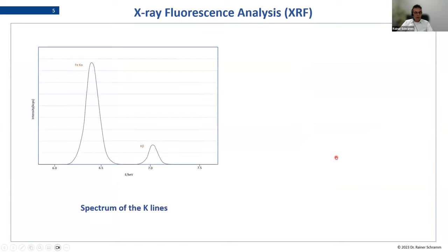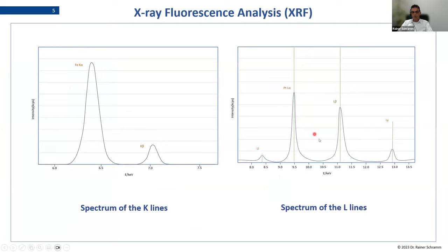But what does this look like? A typical spectrum will look like this. For the K lines, this is the example for iron, we would see such a line pattern, a K alpha line and a K beta line, with a difference of around a factor of five between the lines. And if we look at an L pattern, like here from platinum, we will see these four peaks in different peak heights, which then defines a typical L pattern. What you should also know is that the intensity in energy dispersive XRF comes from the area, the surface of the peak, and in wavelength dispersive, it comes from the height of the peak. Both we call intensity, and for both, all following models are the same. So there is no difference between the two technologies.